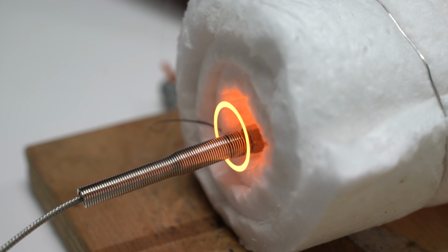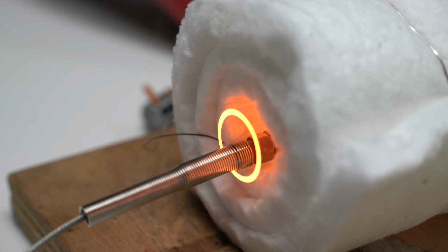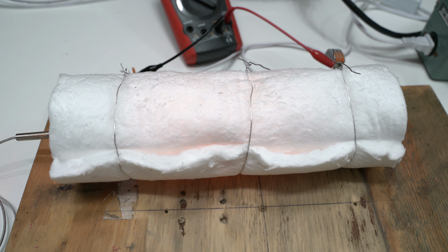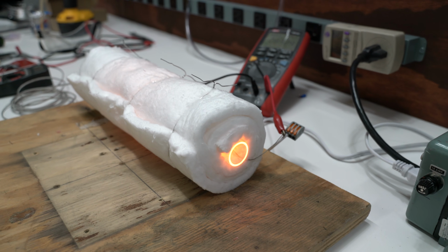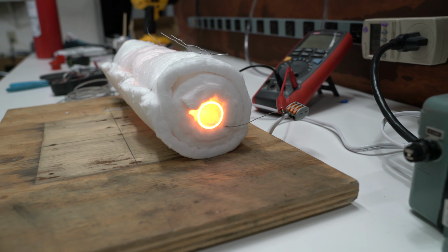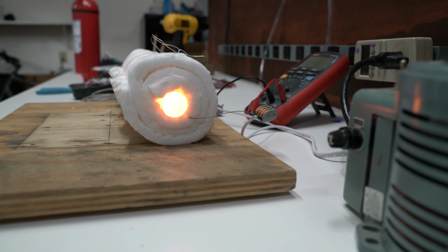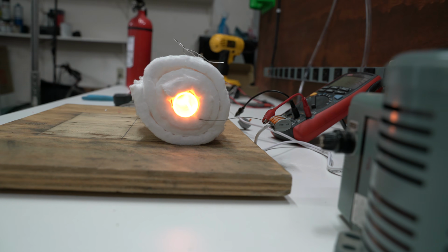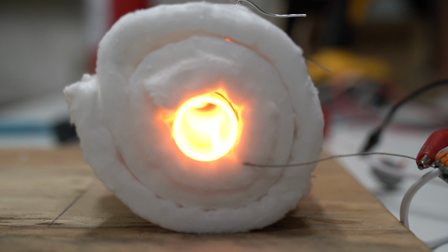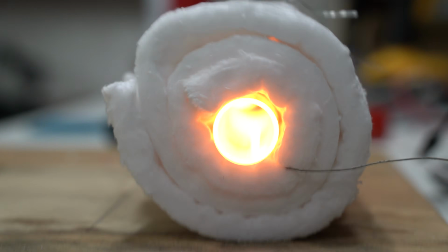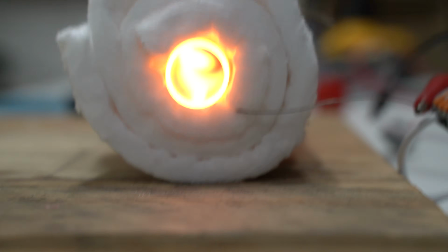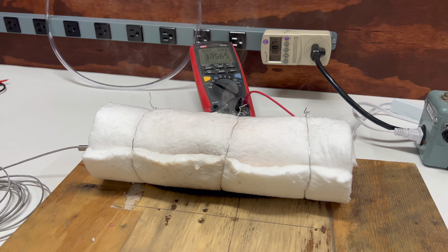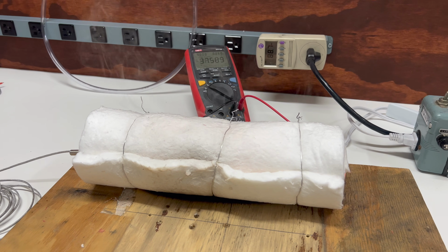The tube is now glowing bright orange, and I'm starting to get some hints that the amount of insulation I'm using is probably not enough. You can see the orange glow from the tube coming through the insulation. Right now, the exterior of the insulation is only about 250 Celsius, and it's resting directly on a scrap of wood, so the way I see it, as long as there's still moisture in the wood, I'm not going to have any troubles, but once that's gone, we're definitely going to have a problem. Yeah, that's no good. Hold on a second while I cool the tube and air out my workshop a bit.